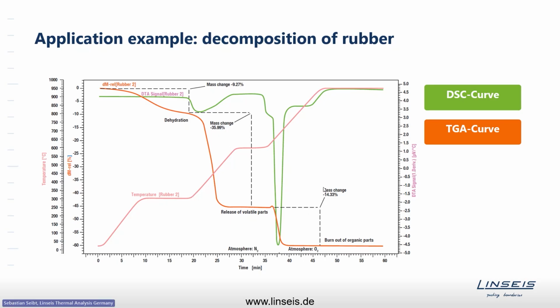Out of this experiment, you can read out the mass change steps. You can read out the enthalpy of this decomposition effect. That gives you information about how much volatiles you have, how much humidity you have, how much carbon content you have, how much residual mass, so inorganics and fillers, you have. And out of this, you can have a pretty good idea how your sample was composed, more or less.